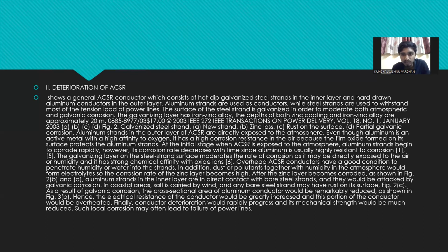After the zinc layer becomes corroded, as shown in the figure, aluminum strands in the inner layer are in direct contact with the bare steel strands and they could be attacked by galvanic corrosion. Hence, the electrical resistance of the conductor would be greatly increased and this portion of the conductor would be overheated. Finally, conductor deterioration would rapidly progress and its mechanical strength would be much reduced. Such local corrosion may often lead to failure of power lines,